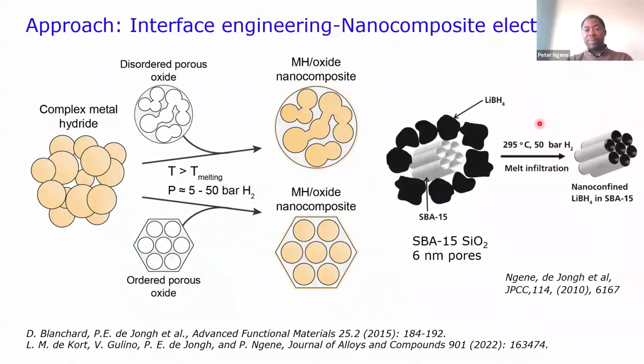This is something I've already done. For example, you have lithium borohydride, depicted here with SBA-15, which is a highly ordered porous silica. You can tune the pores from 3 to even 16 nanometers. If you heat this material above the melting point of LiBH4, it will melt, infiltrate all the pores of this material and stay inside the pore as nano-confined material. In this case, we needed to use an oxide because we cannot use carbon. Carbon is very conductive. If you use carbon with your electrolyte, then you have electronic conductivity, which will result in a short circuit. So we needed an insulator to do this.